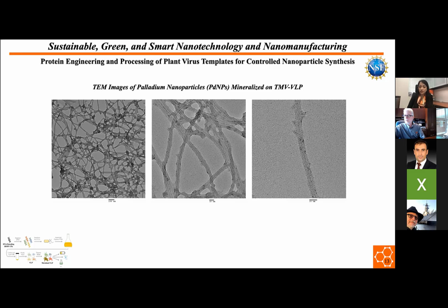However, there are a couple of challenges, including the aggregation of these palladium nanoparticles, as well as aggregation of TMV VLPs. And we are working on different reaction conditions, specifically concentration, pH, and the concentration ratio to overcome this challenge. The other thing that I need to mention is that these TEM images are just after one cycle of coating of TMV VLP using palladium nanoparticles. Usually a couple of coating cycles are used to have smooth and uniform palladium nanoparticles on the surface of a TMV VLP or other biotemplate.